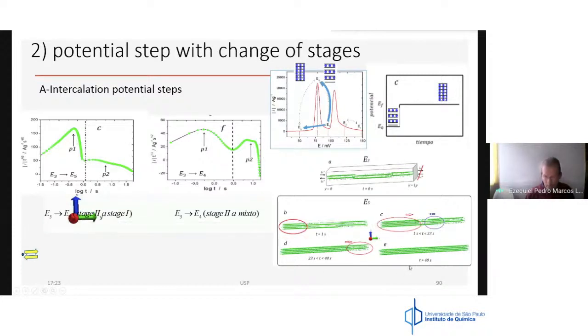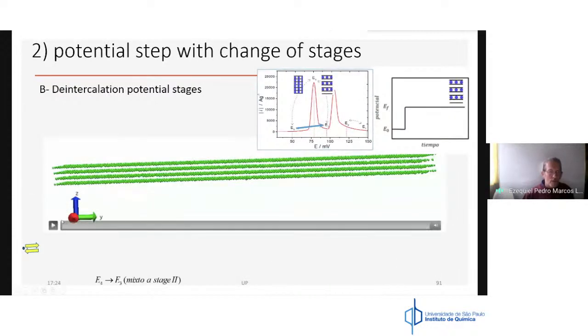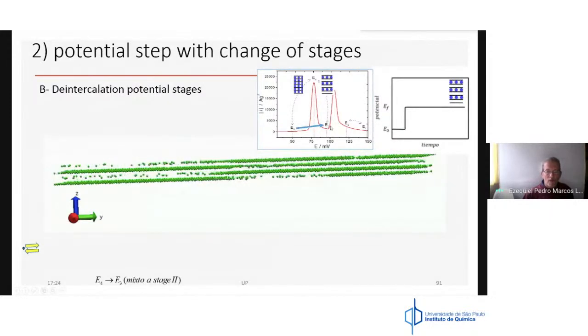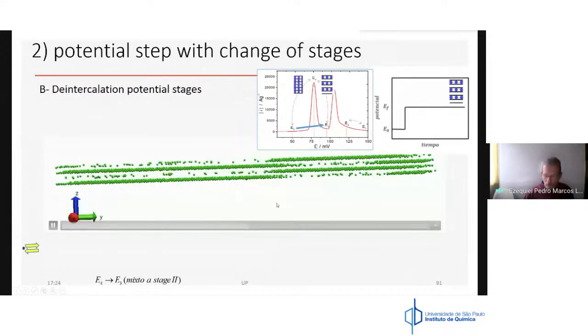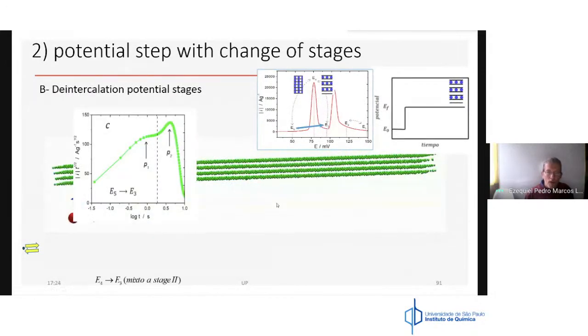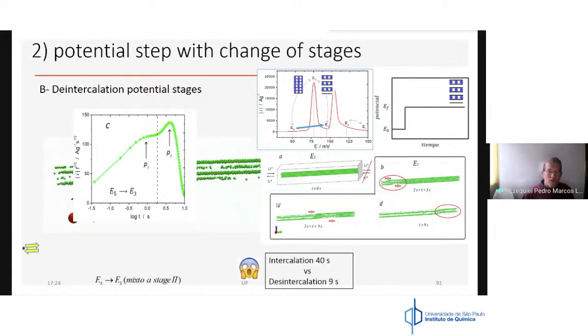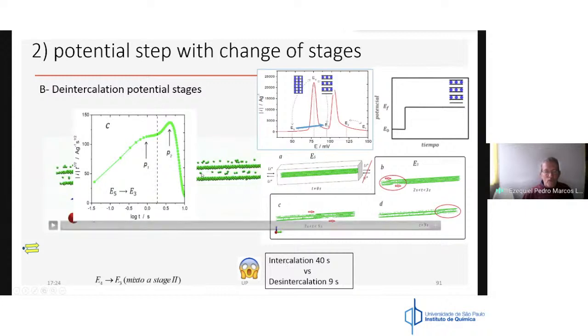You can also, of course, instead of intercalation, do the deintercalation, you can empty. You make a potential step in the opposite direction. You can also see how your system gets empty, and you can also simulate the curves. But the interesting point is that to run from one structure to the other, intercalation takes 40 seconds, but the reverse process takes 9 seconds. That means there is a huge difference between intercalation and deintercalation, and this has to do with the formation of clusters at the end of the electrode when you make the intercalation.